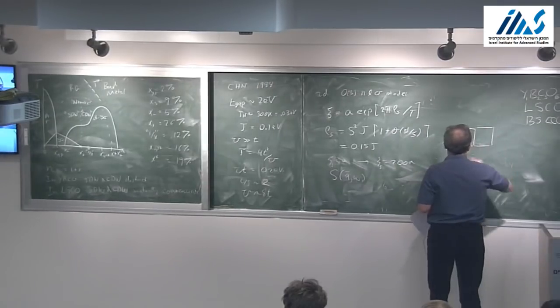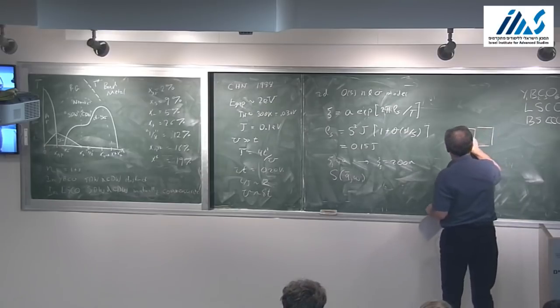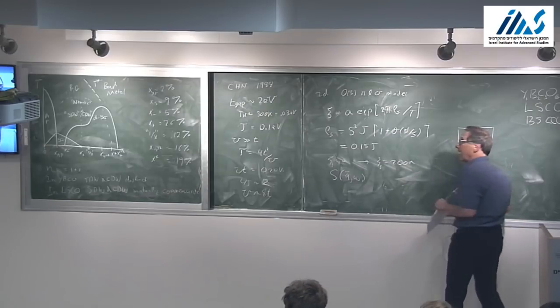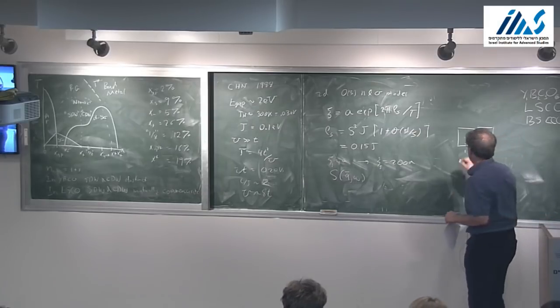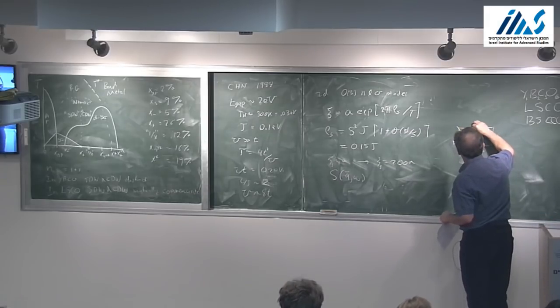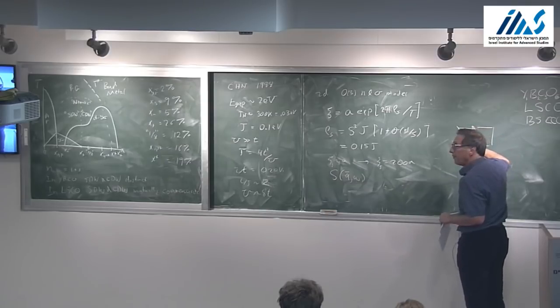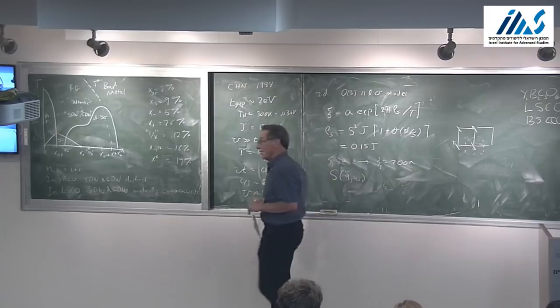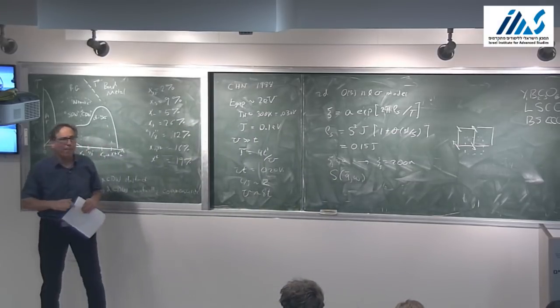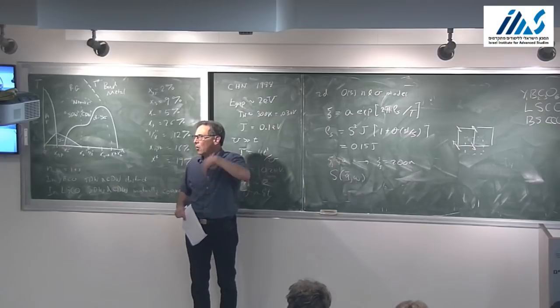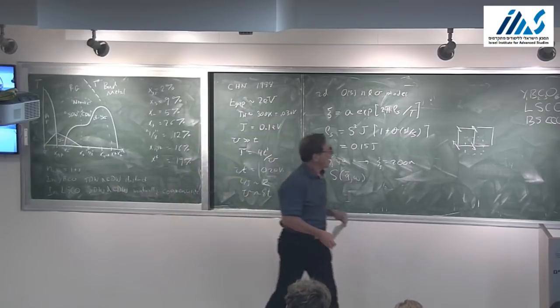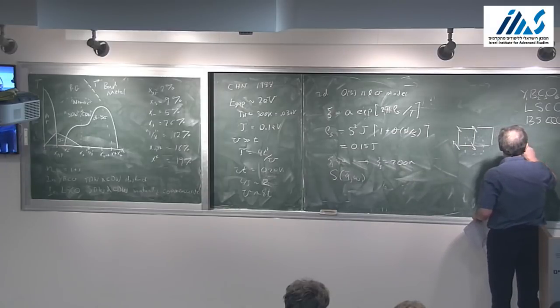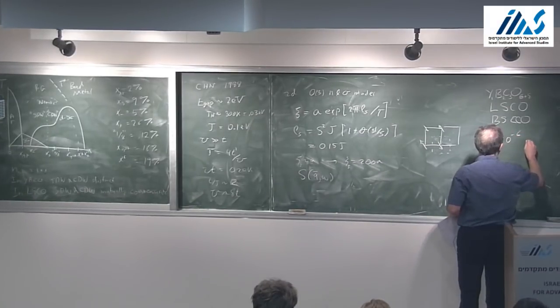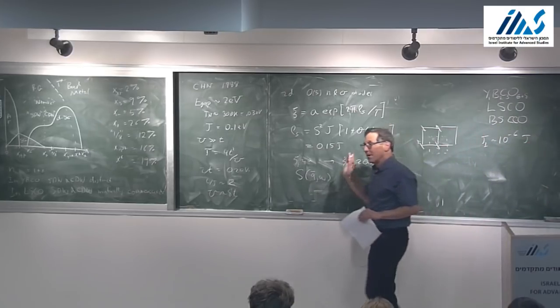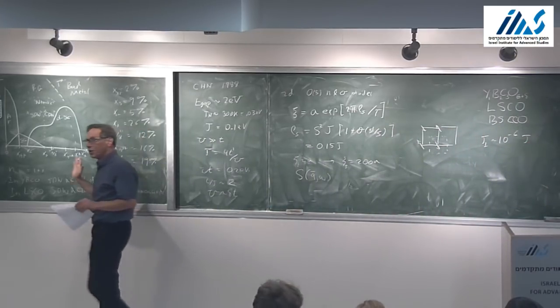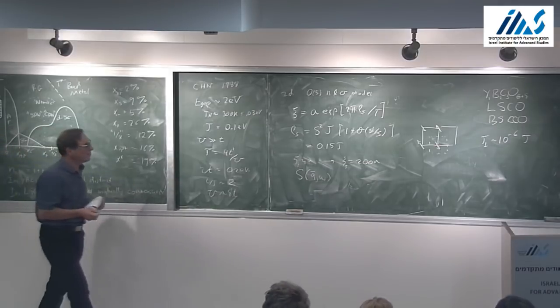But it turns out that for lanthanum cuprate, nature has given us an even better situation because the planes are staggered. So one plane's like this, and the plane above it is offset by this, which means that if you have a Néel ordered state here, the effective field it puts on the next plane is 0 to leading order. And so the effective coupling is either to second neighbor plane or higher order spin couplings. And so the anisotropy, the effective J perpendicular, is something like 10 to the minus sixth times J. So this is really the most two-dimensional antiferromagnet you can imagine.